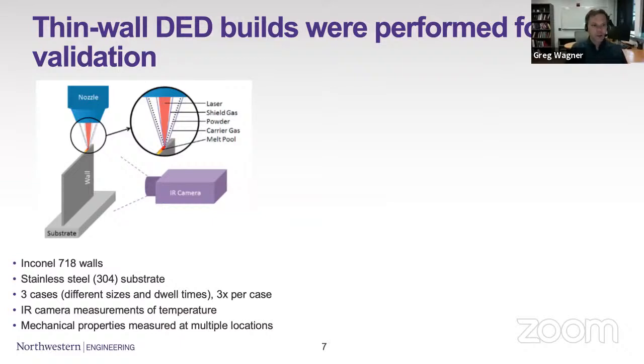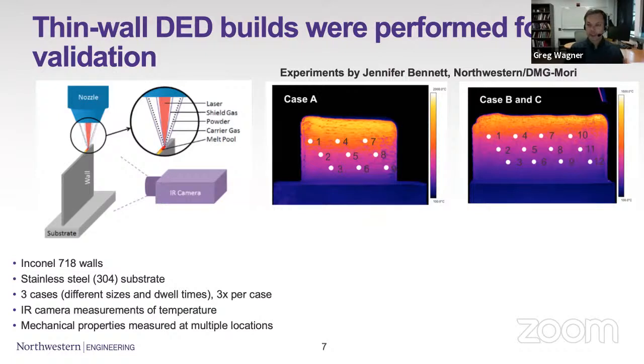These are experiments that were done by basically a Northwestern grad student in a group that we collaborate with, where she built several Inconel walls, Inconel 718, 3 different size walls, or 3 different sets of process parameters at least, so different sizes and dwell times for these different walls, and used IR camera data in order to get temperature histories. By the way, Jennifer Bennett was the student who did this work. She is now an assistant professor, or about to start as an assistant professor at West Point. So this allowed us to get temperature data throughout the part, or at least on the surface of the part, as a function of time.